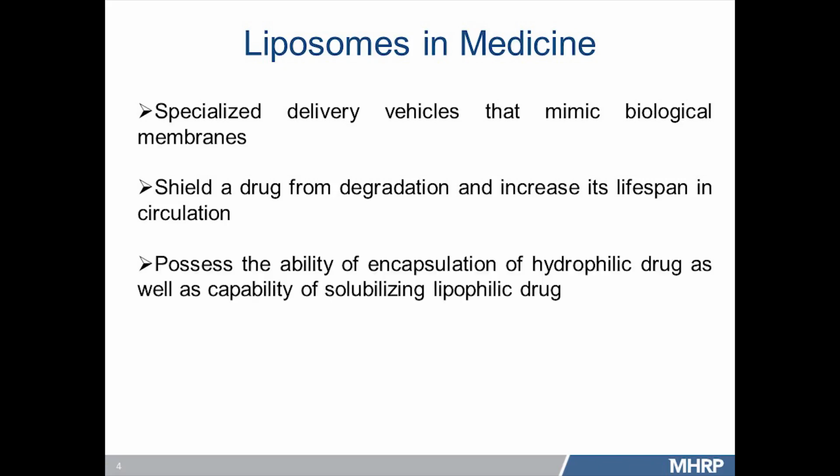Further, they possess the unique ability of encapsulating hydrophilic as well as hydrophobic drugs. They can solubilize hydrophobic drugs. There are examples in the literature where liposomes have been used to solubilize lipophilic drugs about 50 to 60 fold, drugs which are not otherwise soluble and which aggregate when we inject them in the body.